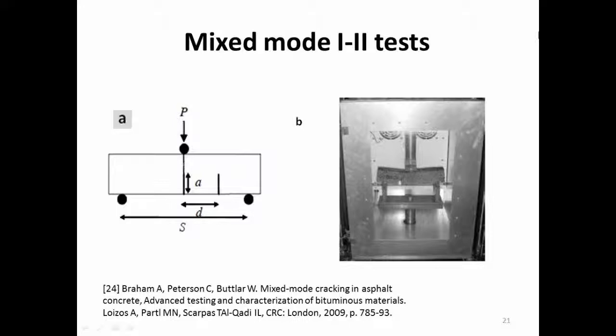You see the crack here, it's not going perpendicular to the edges. But one thing about this test is, if you shift the notch too far away, the crack will not happen here. It will happen in the middle. So how can we control this? They say they know, but I don't know. Okay.